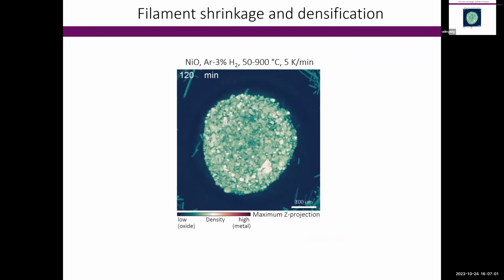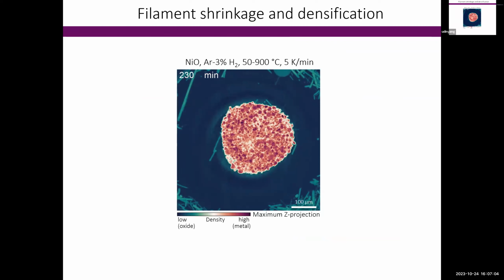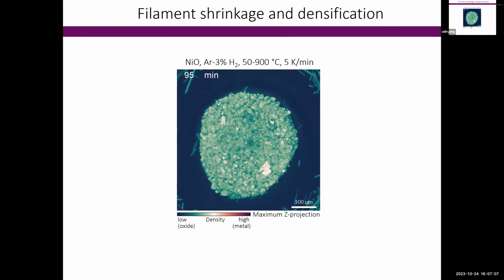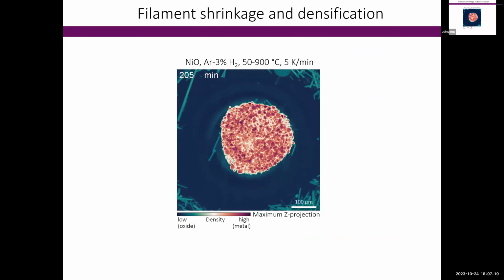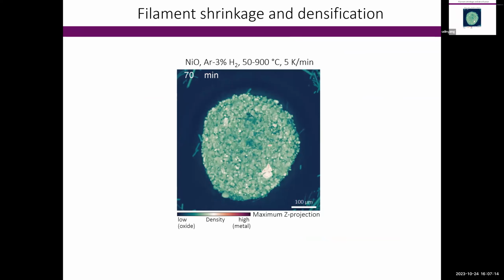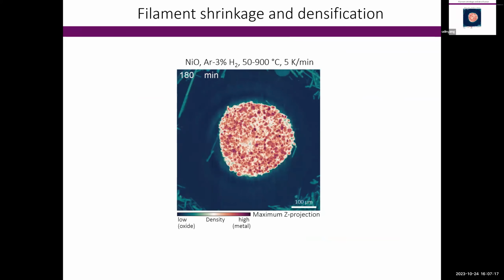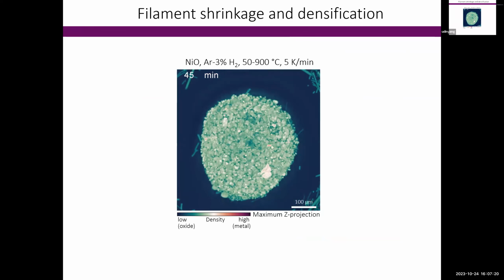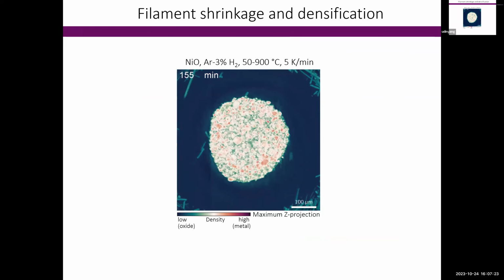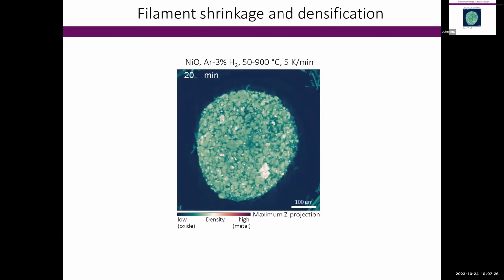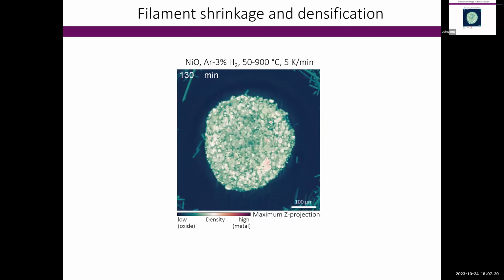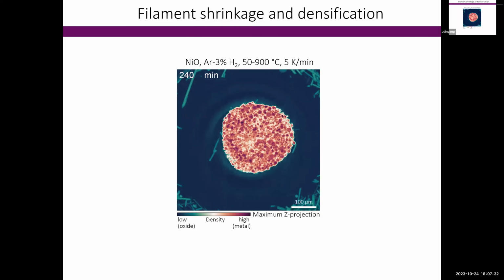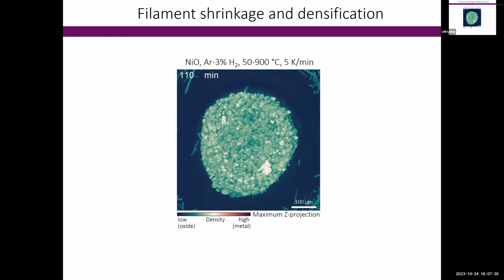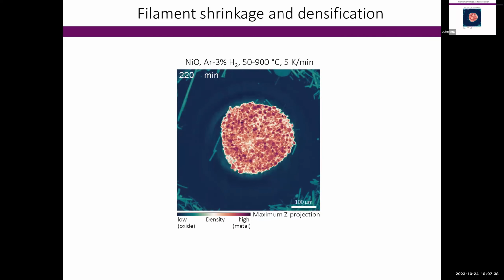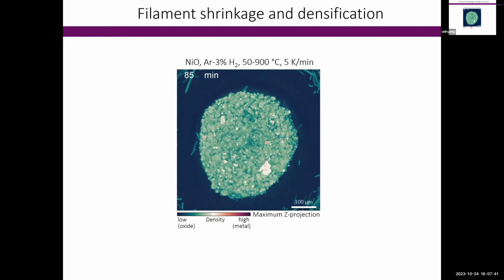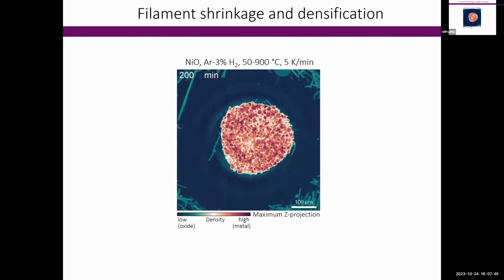Now, the tomography allows us also to see what's inside. Those are in situ reduction tomographic movies showing the shrinkage of a nickel oxide cross-section under hydrogen. The colors represent simply densities, from low density within oxide to high density metal. And you can literally see individual particles that are turning from oxide to metal, and then also sintering, we see the elimination of the empty space. And this is, of course, accelerated. You see the time here, because we need to get full 3D reconstruction. This is just one cross-section.